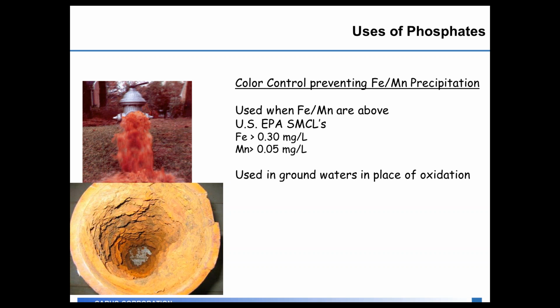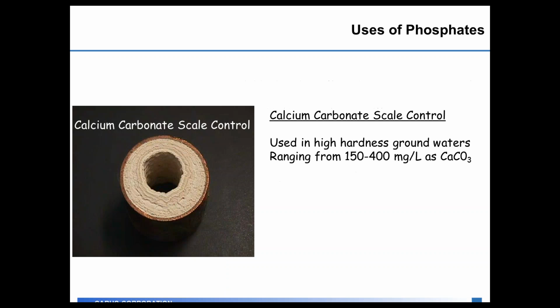Plants that are using oxidation always target to get well below those numbers in the distribution system. In most groundwater plants, if they don't have treatment in place with oxidation and filtration, they can use phosphates for sequestration to tie up the iron and manganese so they won't precipitate out in the distribution system. So they're used in place of oxidation in groundwater.